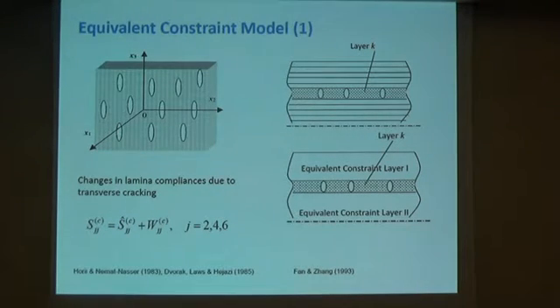Now, knowing stresses in the cracked metal ceramic composite sample, we can estimate stiffness properties of the ceramic sample. For that, we use the equivalent constraint model. Generally, we assume that when a series of parallel cracks is present in a solid, this will lead to changes in compliances of that solid. Only our solid is not infinite as shown here and as was used in these classical models. Our solid is a layer squeezed between two other layers, so we need to take into account that constraint effect of the layers on the cracked layer, and that's what the equivalent constraint model allows us to do.